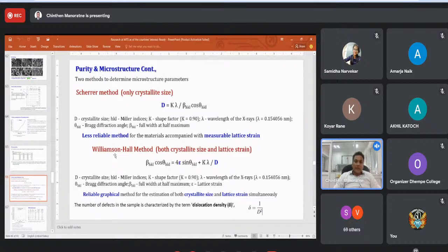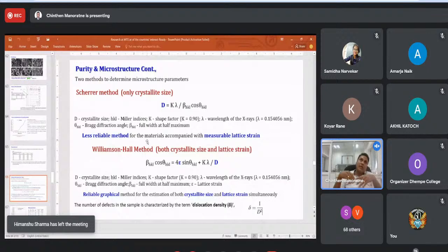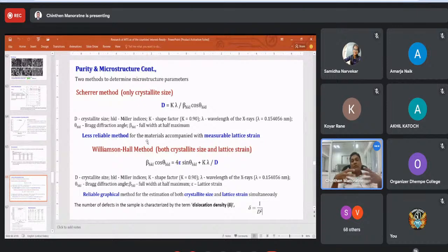Now, for that, we used the XRD graph for this microstructure analysis, where we employed the Scherrer method and the Williamson-Hall method for both crystallite size and strain to understand their structure. Based on these data, we calculated dislocation density. It is essential to know the microstructural behavior at elevated temperature, because our final electrochemical reaction takes place at elevated temperature. So we should know what will happen within these materials at that temperature. That is why we study this basic, preliminary data for our next level research output.